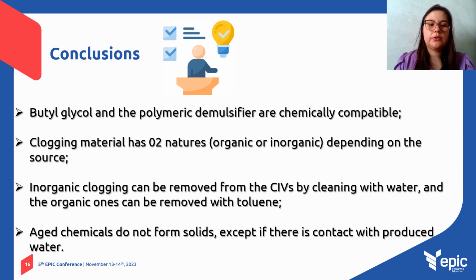According to all the results presented, some conclusions might be highlighted. Butylglycol and the polymeric demulsifier are totally chemically compatible. The clogging material has two natures, organic or inorganic, depending on the chemical injection valve source. Inorganic clogging can be removed from the chemical injection valves by cleaning with water, and the organic ones can be removed with toluene cleaning. Aged chemicals do not form solids, except if there is contact with the produced water.